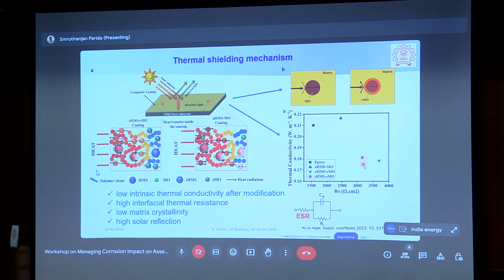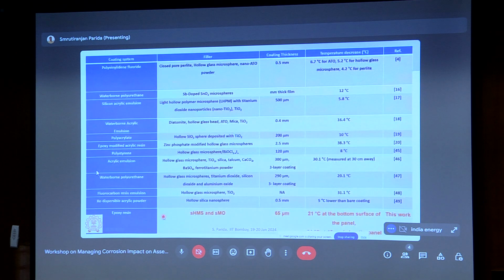So this is one of the combination of tests that we do. Thermal conductivity is compared with the ESR, equivalent series resistance. Equivalent series resistance is basically an indirect representation of the decrease in the crystallinity of the matrix. As you can see here, if the equivalent series resistance is increasing, then thermal conductivity is decreasing. That indirectly says that the matrix crystallinity has decreased drastically. If we compare with different literature data, please compare the thickness as well as the decrease in temperature. You can see people have used 300 micron, millimeter type of coatings, but their effective temperature decrease is not very significant. But in our case, we have reached 18 to 21 degrees at different levels.